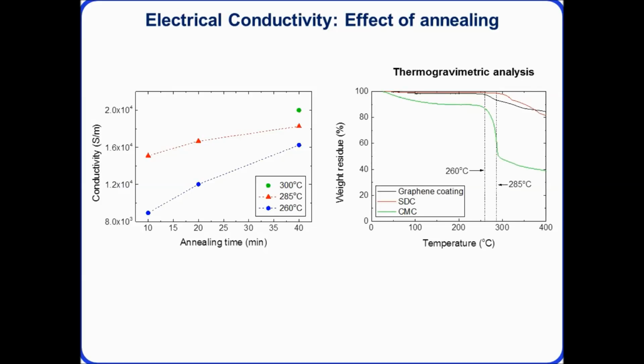So this is a thermogravimetric analysis plot, and that's just showing at these high temperatures we are starting to decompose some of the surfactant we're using, which is called sodium deoxycholate, and also we are starting to decompose the cellulose. In this case, we're using one called carboxymethyl cellulose. So that's starting to decompose beyond 260 degrees, and we can remove around 60% of that material after around 300 degrees.